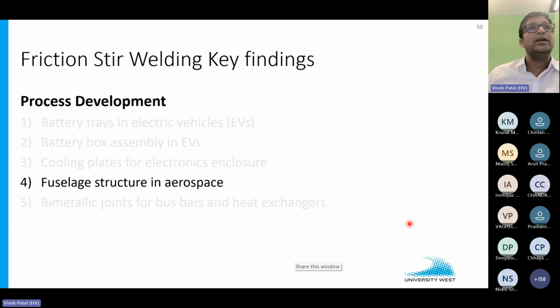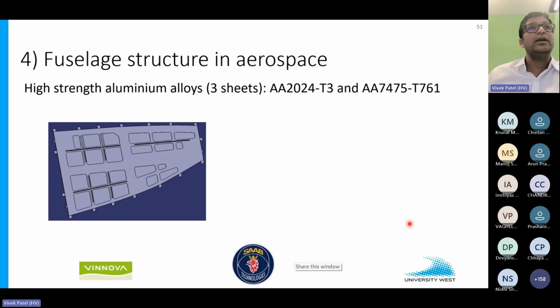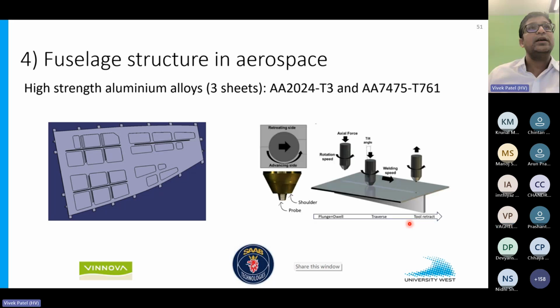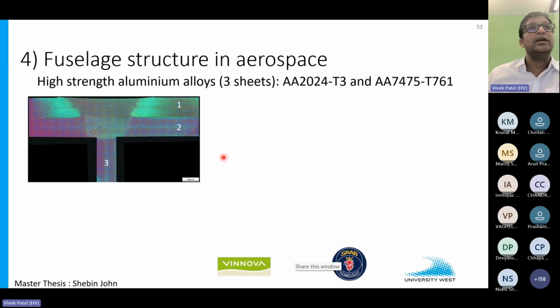So some applications now, for some aerospace applications. In aerospace, you see a lot of friction stir welding happening for fuselage made of aluminum, light metals, and the grades are typically 2000 and 7000 grades. So we tried to have T joints, and we wanted three sheets together for one of the applications for an engine component. And you can see the cross section. There is sheet material 1, material 2, and material 3 in a T joint configuration, and we wanted to join these three materials together.